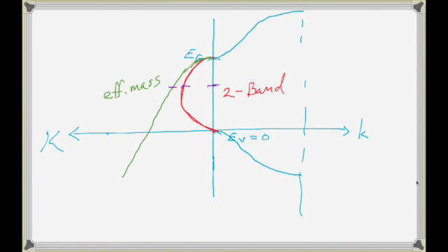If, for example, I'm down here, and this is exactly what happens in this indium arsenide aluminum antimonide problem, which I'll show in a second. The other thing is that right at the midpoint, when E is Eg over 2, it's 2t sinh kappa A over 2.